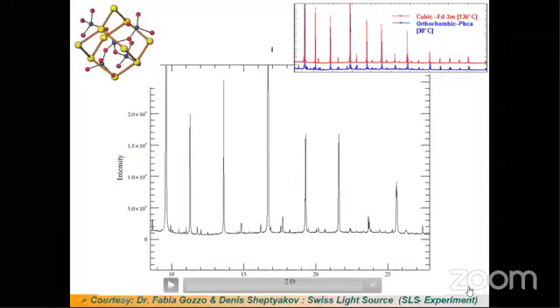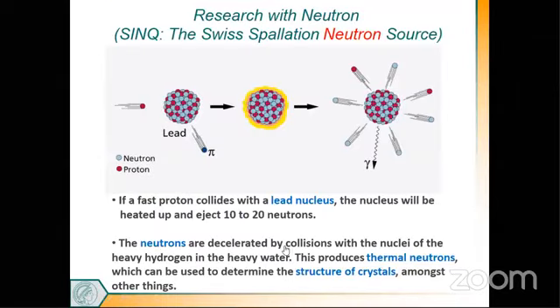Apologies. Okay, now. Another technique to measure this rotor mechanism is neutron powder diffraction, because we are looking at the oxygen rotation. The contrast for seeing oxygen via neutrons is better than X-ray diffraction, because the neutron coherent scattering length b for oxygen is better than for X-rays. So we use neutron spallation sources, which I don't want to explain here.